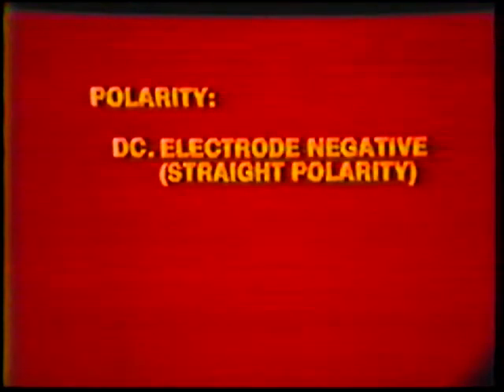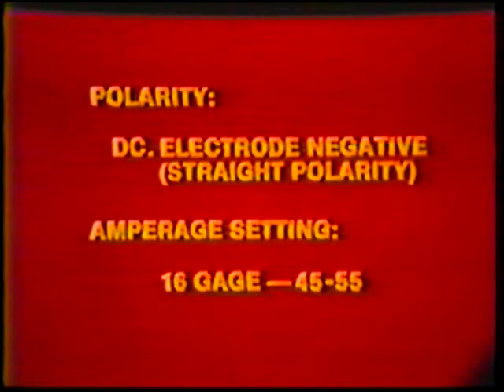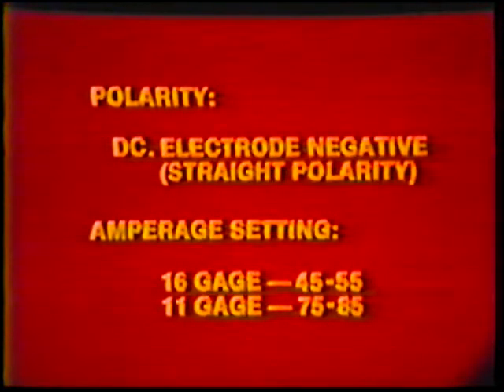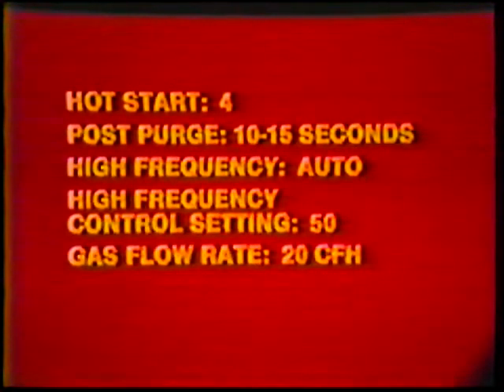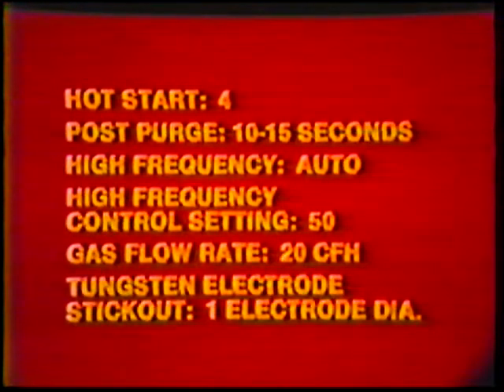Machine settings. Polarity: direct current electrode negative, straight polarity. Amperage setting: 45 to 55 for the 16 gauge, 75 to 85 for 11 gauge. Hot start: 4. Post purge: 10 to 15 seconds. High frequency: automatic. High frequency control setting: 50. Gas flow rate: 20 cubic feet per hour. Tungsten electrode stick out: 1 electrode diameter.